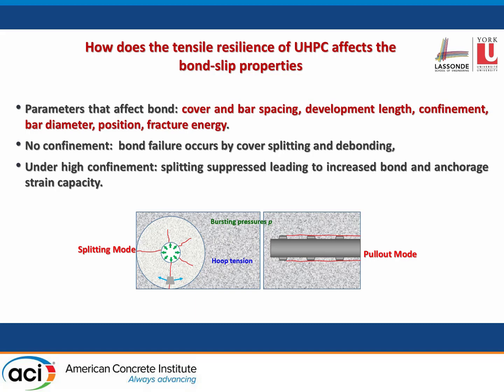So the question that came to my mind, the motivating question, was how the tensile resilience of the UHPC materials may affect or may strengthen or enhance the bond slip properties of reinforcement embedded in these materials. The reason this motivation came about is because we know that confinement is a critical parameter that affects bond. In the absence of any confinement, we have bond failure occurring by cover splitting. But we do know that we can change this mode of failure to something generally referred to as pull-out by the addition of a significant amount of cover, by the addition of confinement, by enhancing the development length, by reducing the bar diameter, and by enhancing the fracture energy of concrete. And many of these parameters really are reflected through the tensile resilience of UHPC.